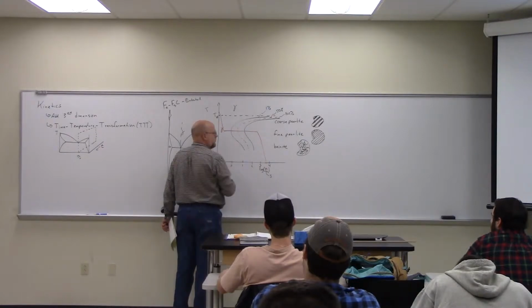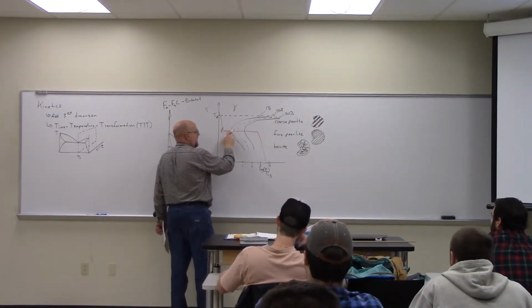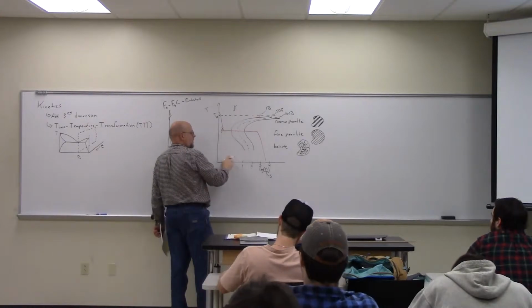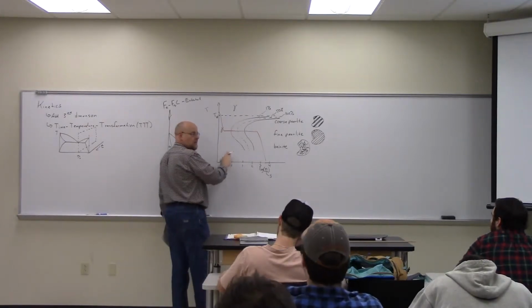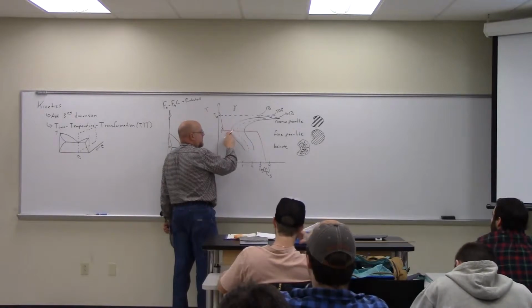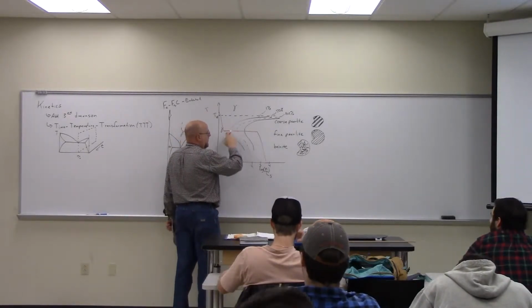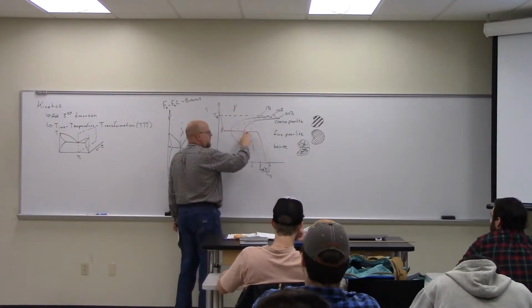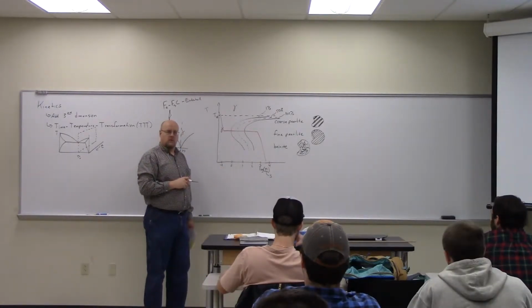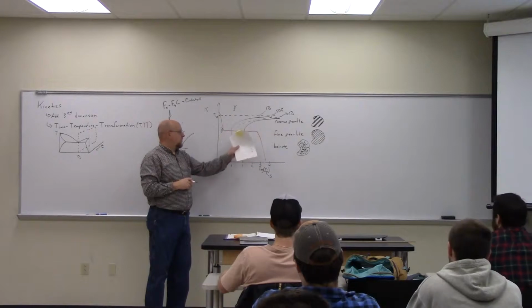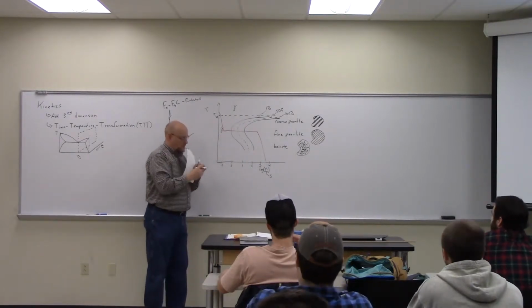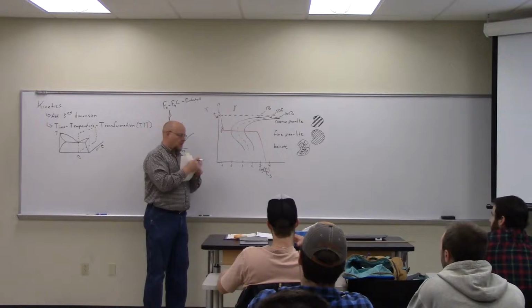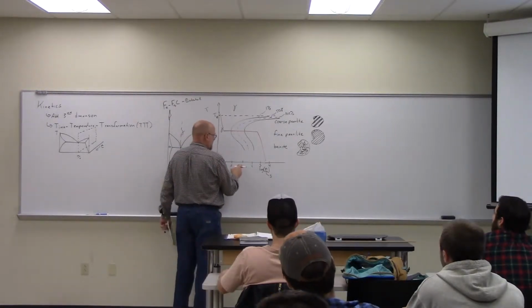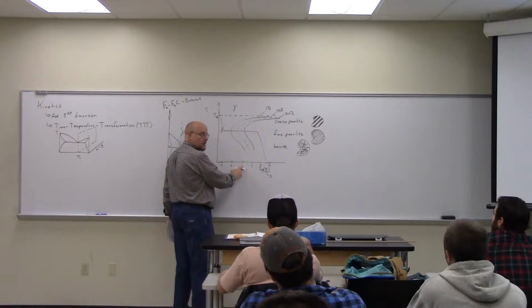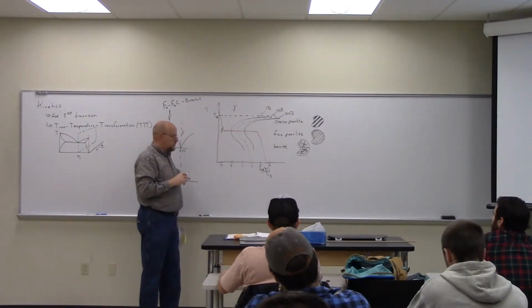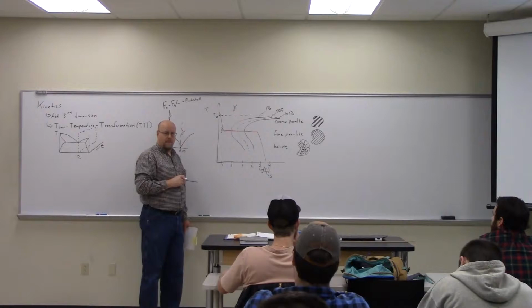and then cool it down to room temperature, that says that at this point in time, at 1 second, I begin forming fine pearlite, and over here at about 10 seconds, I finish forming fine pearlite. I go from 0% transformation to 100% transformation. Where's the 10 seconds? Right there. 10 to the 1 is 10. Okay, I didn't see that. It's kind of a long scale.